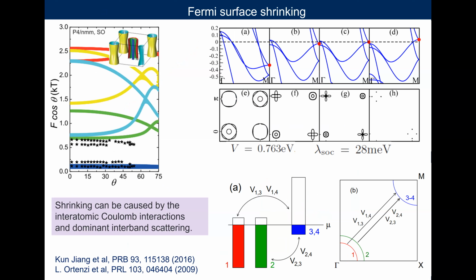Now, why does this shrinking occur? This is quite unusual. We discussed that correlations are very important, and how the shrinking occurs is very unusual in that both the electrons and holes are shrunk together. Here are the data from quantum oscillations, and these are the predictions from DFT. We have pockets about a factor of 5 smaller than what the calculation predicts. These are some theoretical calculations including the nearest neighbor interaction in the presence of spin-orbit coupling, and those types of interaction indeed can lead to shrinking of the Fermi surfaces. Another important thing we have here is the nesting effects: the interband interaction between hole and electron pockets can also lead to this severe shrinking of Fermi surfaces.